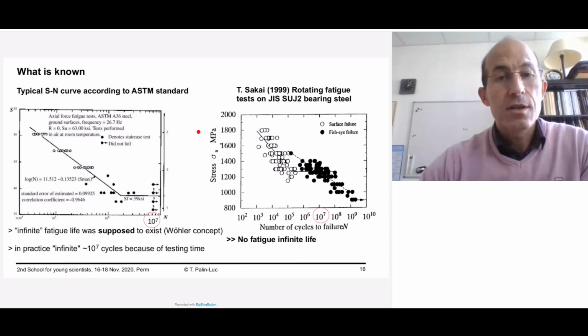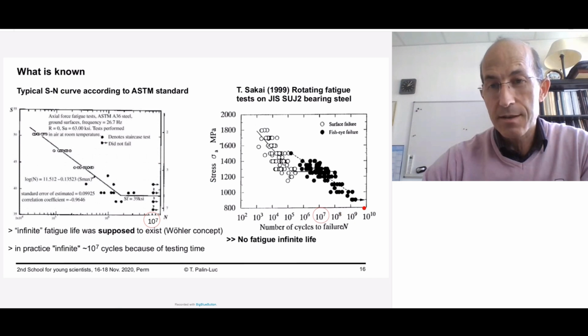Such fish eyes are observed typically on industrial alloys. The consequence of such evolution of the fatigue crack initiation mechanisms is very important for engineers designing structures, because if you have a look at the ASTM standard, there is a typical SN curve with an asymptotic tendency according to Wöhler's assumption. In practice, this asymptotic tendency corresponds to 10 to the 7 cycles, because at that time it was very difficult to do many more cycles in a test in a reasonable testing time. But look, for instance, at the famous experiments by Professor Sakai in 1999 on a bearing steel: if you exceed 10 to the 7, if you go to 10 to the 9 or 10 to the 10 cycles, the asymptotic tendency doesn't exist anymore, and there are cracks or failure, so there is no infinite fatigue life.